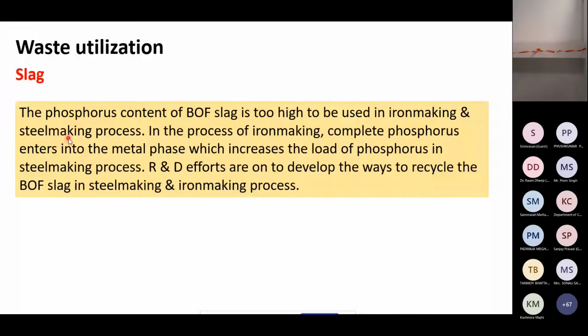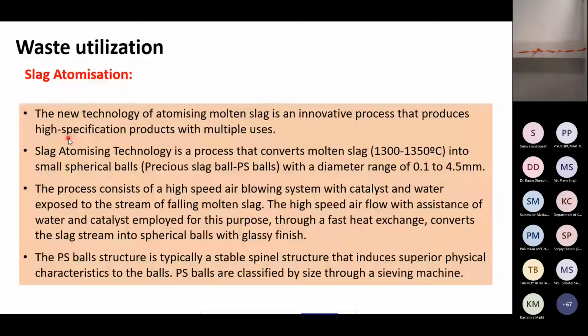So by any way, if the phosphorus in this slag can be reduced, the utilization can be very easy, because the iron content from these three S's, that is scale, slag and sludge, is more than 50%. But we cannot directly recycle it in the steel making process. The reason is simple: it contains manganese, chromium, phosphorus, calcium, silica, different kinds of oxides and fused materials, and it prevents the direct recycle of this waste into the steel making process. And one of the technologies is slag atomization.